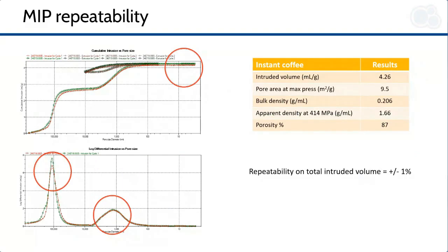Mercury intrusion porosimetry, when performed with the proper analytical method and with a reliable instrument, is a very reproducible technique. In case of this instant coffee, the reproducibility on the total intruded volume is about 1%, on the pore size even better. The total surface area is about 9.5 square meters per gram, and the apparent density calculated at 414 megapascal is 1.66 grams per milliliter, much higher than the density measured by the pycnometer using nitrogen.